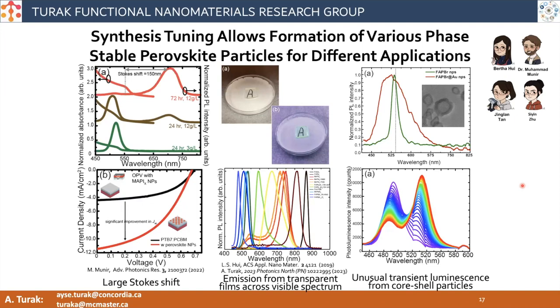This also allows us, as I said, to get this kind of full spectrum of emission from what are basically transparent films. So the nice thing about it is we make this monolayer, they're mostly transparent under optical conditions. Unlike a lot of perovskite systems that you may have seen, they're quite black because they absorb a lot, right? That's the whole point. But these systems are basically transparent, yet we can get illumination from these transparent films. So this opens up new avenues for window coatings, things like that. So there's some possibilities there.